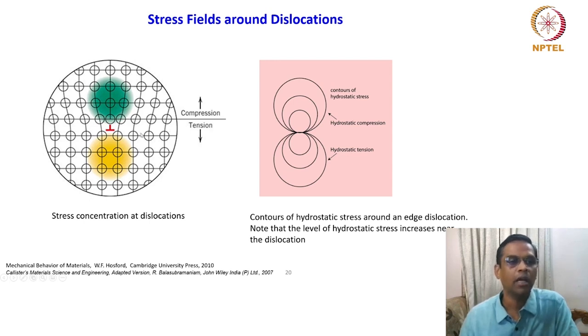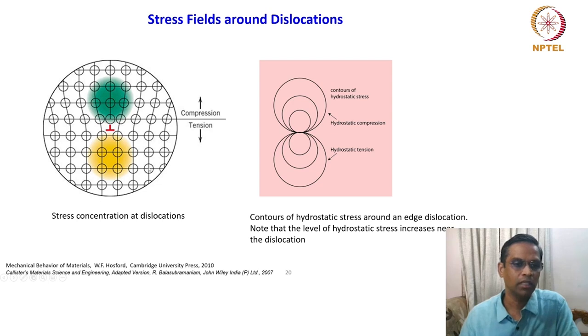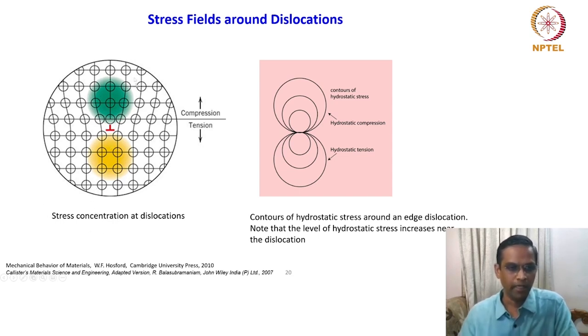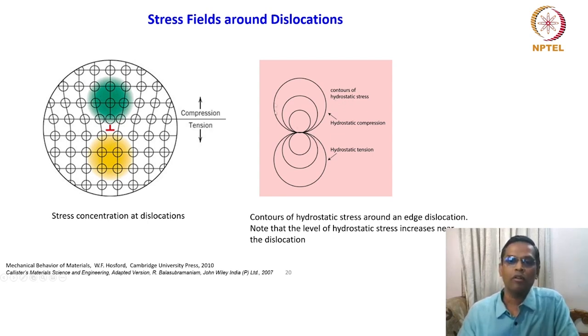What you have to appreciate here is that above the extra half plane, the stress field is quite different compared to the bottom of the edge dislocation. The above half will experience a compressive stress and the bottom half experiences tensile stress. But if you get into the details, it is much more interesting — the contours of the stress fields are shown here, and it is not simple compression or simple tension, it is hydrostatic stress.